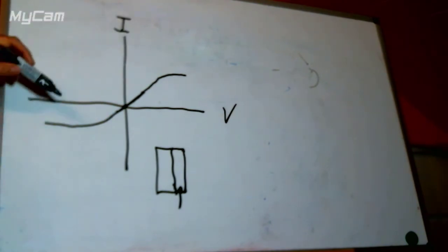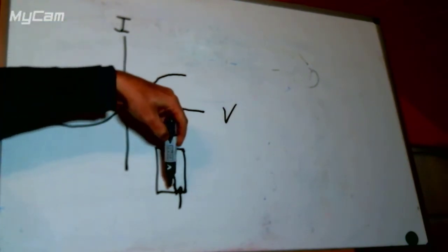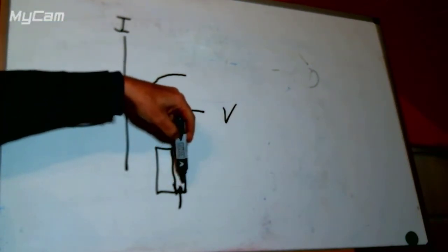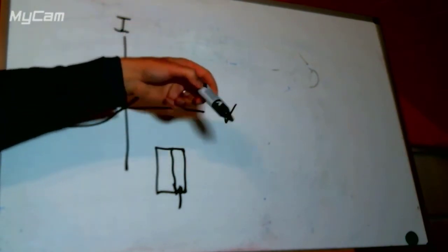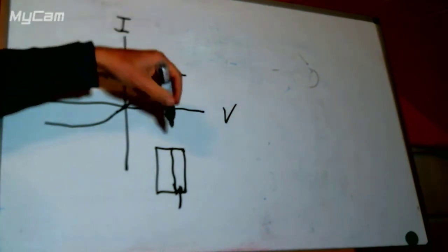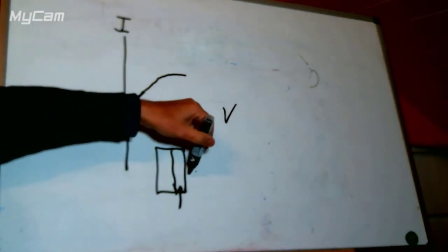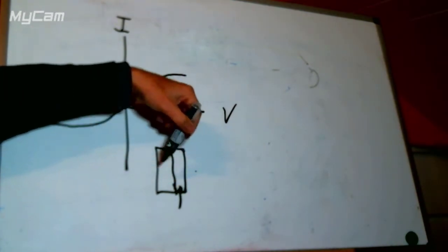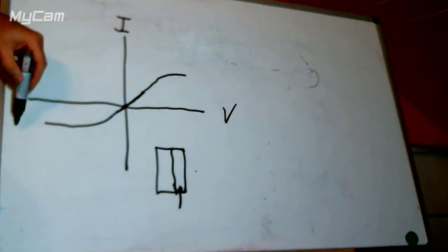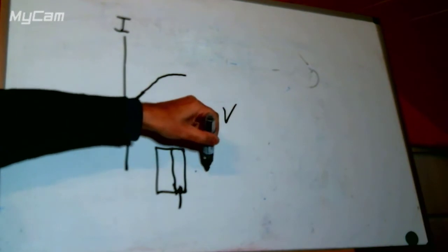It's not necessarily symmetrical, because this effect here on this direction, we're using up the ions that are already in solution, and we've got 0 here. It turns out, weirdly, so this is possibly a difficult concept. I know this is sometimes a difficult concept. It turns out that once we've got the concentration down to 0, in close to the electrode, it doesn't matter what voltage we put on. We cannot get more ions to come further, faster.